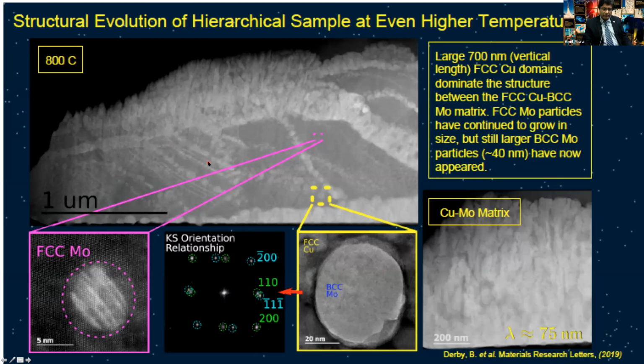What is interesting is that there's a bimodal distribution of precipitates. You still see some FCC moly precipitates. The sizes have increased up to a little less than 5 nanometer or so. But a lot of the moly precipitates have now become BCC. So at 800 degrees C, those have coarsened and transformed from the metastable FCC to the equilibrium BCC structure of moly. They don't have the three-dimensional superlattice, but they do have the linear arrays that are forming. So it is sort of structure inside structure, nanocomposite inside nanocomposite.